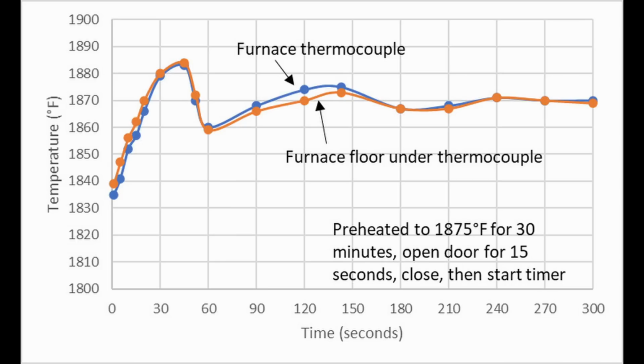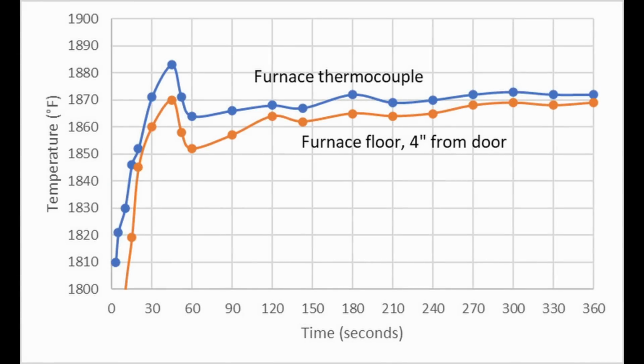With a loaded up furnace, there will be some variation in temperature. Those knives that are close to the thermocouple will be dead on, and the ones far away from the thermocouple may be off by some amount. That can be a few degrees, that can be 20 to 30 degrees plus, which is the difference between the blades in the center and the blades that might be in the corners of a furnace.